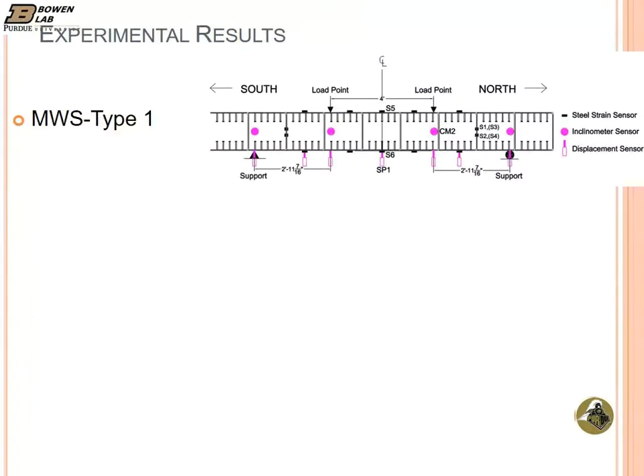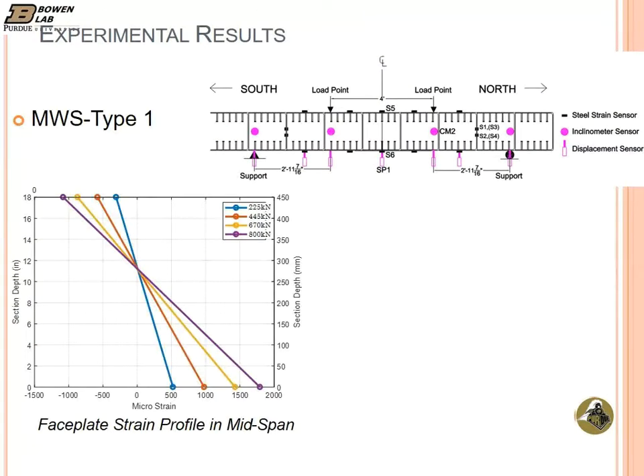Now we're going to look at the strains. First, looking at the faceplate strains S5 and S6. This is the strain profile that we developed by connecting the gauge readings: the top faceplate strain is negative, the bottom faceplate strain is positive, at different load levels. You see the neutral axis remaining at the same location, about 1/3 of the section thickness, and the strength was 800 kilonewtons. When we looked at the strains on the faceplate, you realize it's less than 2,000 microstrain, and the yield strain was 2,070. So that also indicates that we had shear failure, not any flexural yielding.